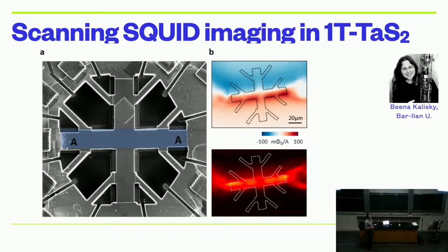But what's going on? Well, again, I collaborated with my favorite squid collaborator, Bina, who's now at Bar-Ilan University. And she could take one of our devices and actually use the squid technique to image the current. So when you apply a small current on the system, you have a Biot-Savart field from the current itself, and that's the blue; these are the polarities of the field on either side of the flowing current. And you can take the derivative of this data and look at the current density. So what you can see across this device is where the current is flowing.